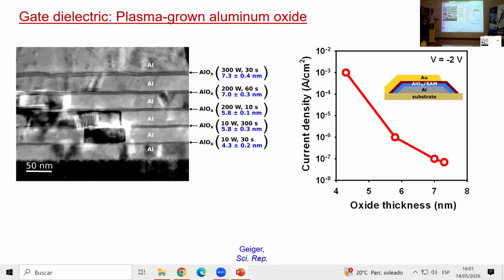And there's a second reason, and that is the cleanliness of this interface. We just talked about trap states. And one important contributor to trap states is a hetero interface. But if we grow aluminum oxide on aluminum, it's a native oxide. And that will have the smallest possible interface trap density, as opposed to if we were to deposit aluminum oxide by ALD onto a different type of surface, then we would immediately have a hetero interface and thereby a larger trap state density. So those are the two reasons why we prefer the oxidation process over the deposition process.